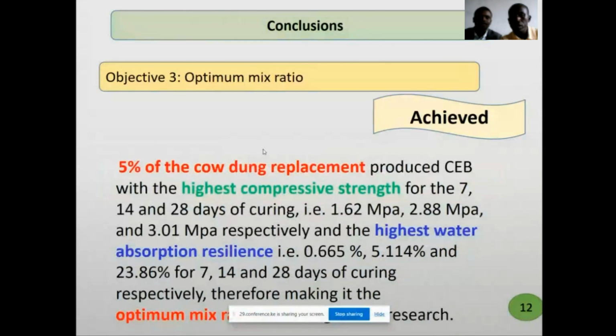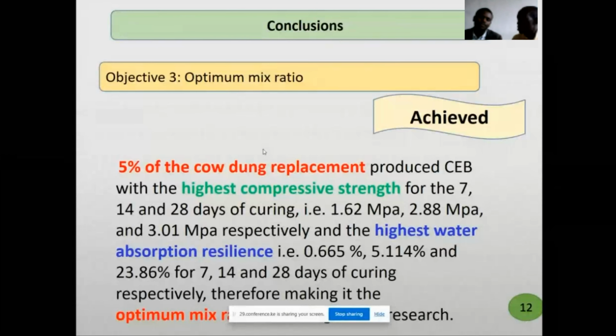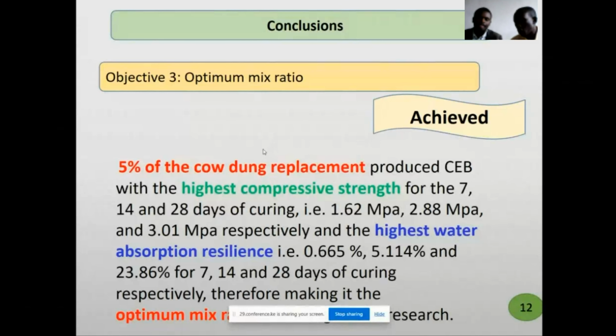Objective number 3 was also achieved because we determined the optimum mix ratio for our research work. And we found out that the 5% cow dung replacement produced CEB with the highest compressive strength in all the days, the 7 days, the 14 days, and 28 days. The values are given there. And this gave us the highest water absorption resilience, which is also indicated there. So our optimum mix ratio is 5%.